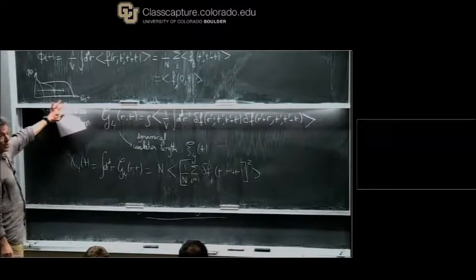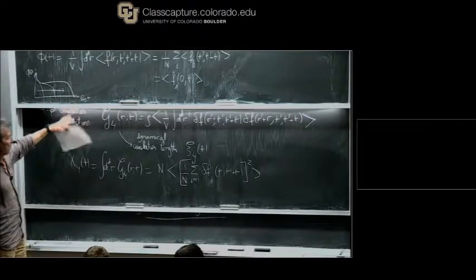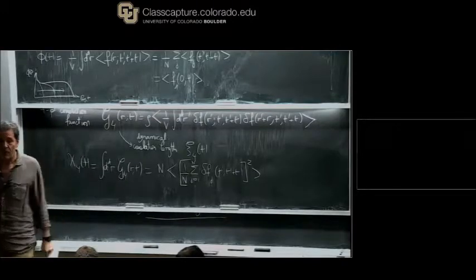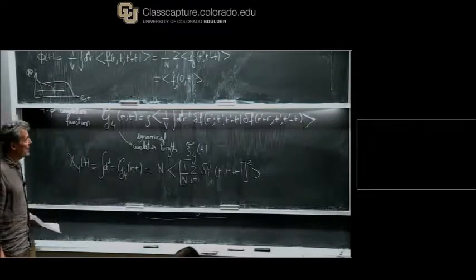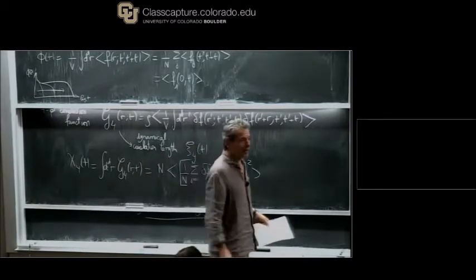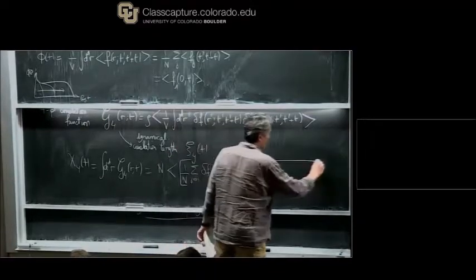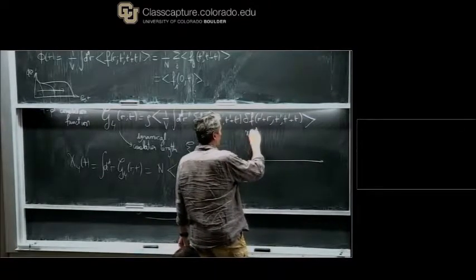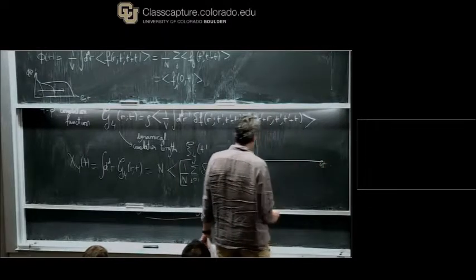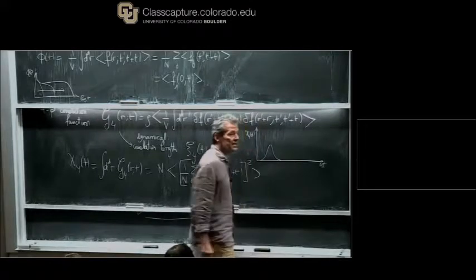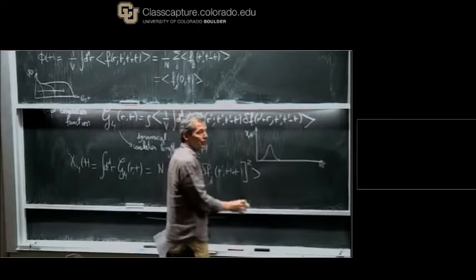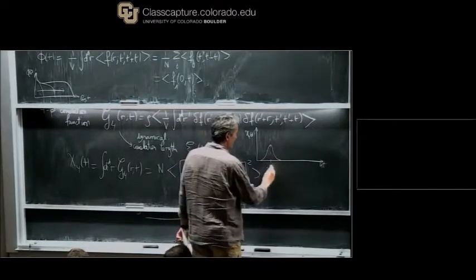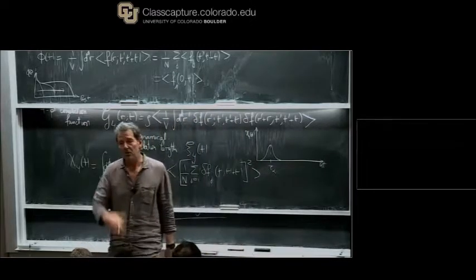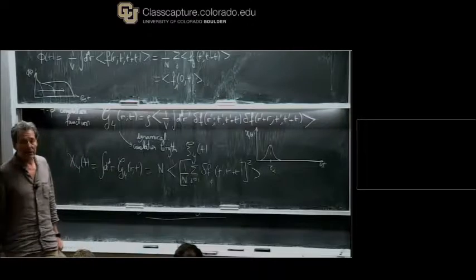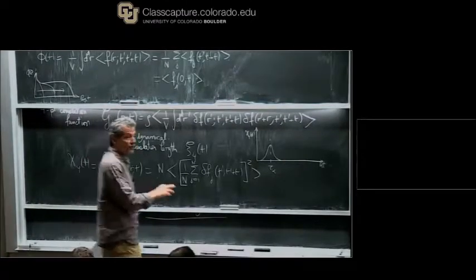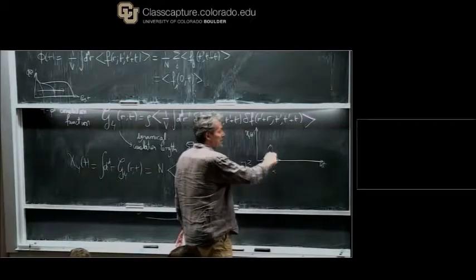But it is very interesting in terms of time scale, but it has no length scale. To go to length scale, you need now, again, 4 points, and this is the quantity that carries information. Now, this has been measured in simulations and in colloids, and basically the behavior is that it goes through a maximum, because as I said, the system is homogeneous at short times, homogeneous at long times, and the maximum is around the alpha relaxation time. Not exactly a factor of 2, 4, but about the alpha relaxation time. So this function, as a function of time, has this behavior at a given temperature. It increases and goes down.